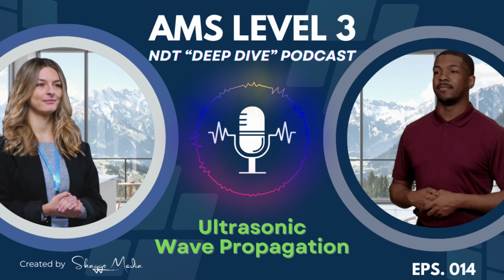First, the energy that would have gone into the longitudinal wave now generates a specific type of reflected surface wave. It's distinct from the Rayleigh wave we just discussed. And second, the reflected transverse wave now has a reflection coefficient of -1. So its amplitude is the same, but it's completely flipped, a 180-degree phase shift. Exactly that.